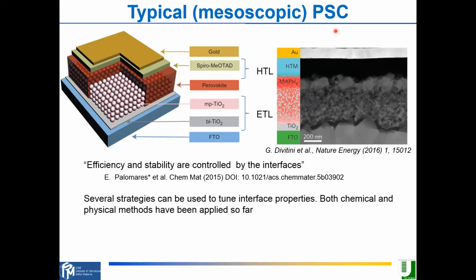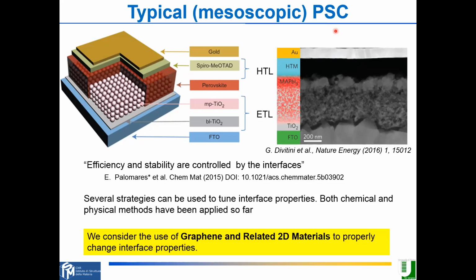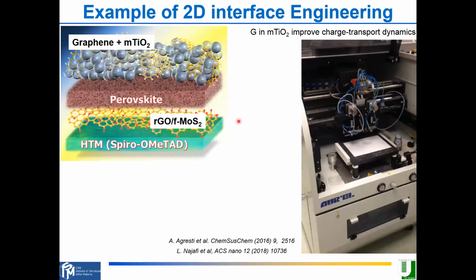So you can do it in several ways. We proposed some time ago to use 2D materials like graphene and related 2D materials. So we started this journey supported by the Graphene Flagship of the European Community. And you see then we made a lot of effort in this way. For example, this is an example where we were using graphene flakes in titania. And on the other side, we use reduced graphene oxide and functionalized molybdenum disulfide, a sort of van der Waals 2D crystal, at the interface between the hole transporting layer and the perovskite. So this was the arrangement we did.